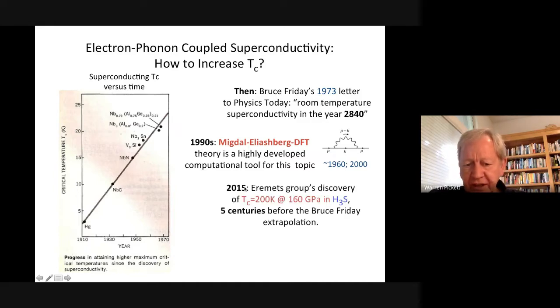Now, 2015, and I'm jumping ahead to near the end of the story, but Mikhail Eremets' group in Mainz discovered a TC of 200 Kelvin at a very high pressure of 160 gigapascals. This is 1.6 megabar pressure, million atmospheres of pressure, in hydrogen sulfide, which, of course, is not 5 centuries, it's actually 8 centuries before Bruce Friday's extrapolation. No, if you just go to 200 Kelvin, it's 5 centuries. That's why I wrote it that way.